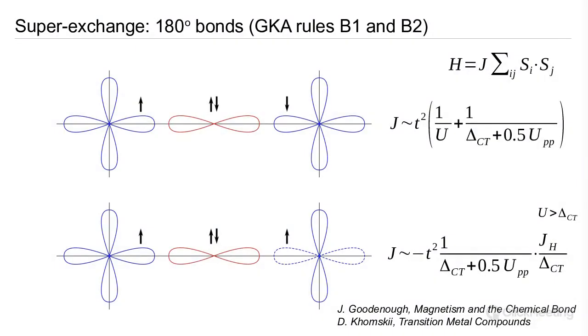We can go one step further, and we can put an oxygen atom in the middle, and this is what's known as superexchange. So if we think about superexchange on a 180-degree bond, the spins are still largely localized in this system, but we might think that we've got a problem, because we might think that these two paired electrons in the middle here create, if you like, a magnetic block between these two atoms. We have this non-magnetic oxygen p orbital in the way. But what actually happens is that the energy of the system is lowered if these electrons can be deconfined, if they can hop across the bond.